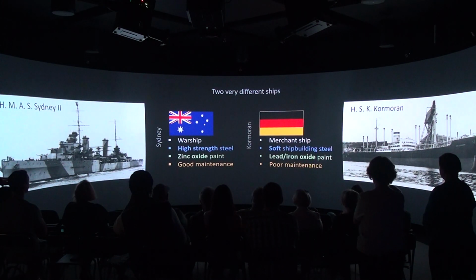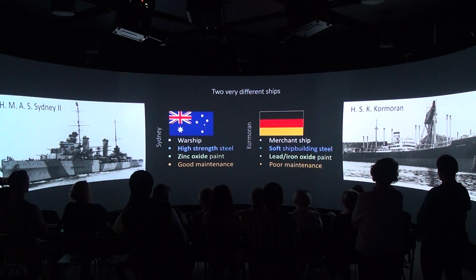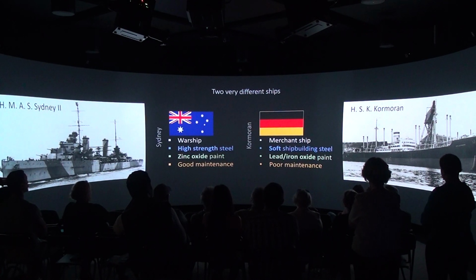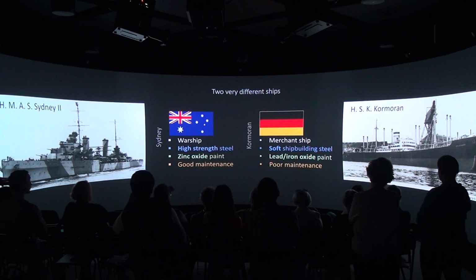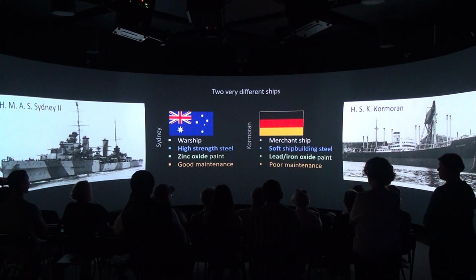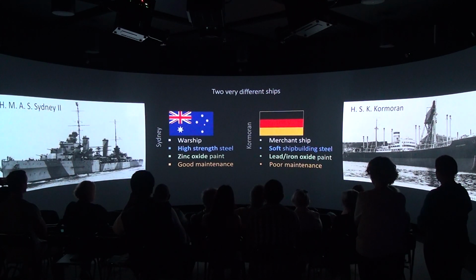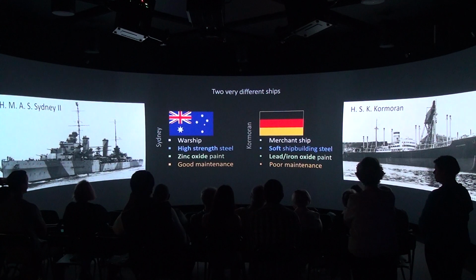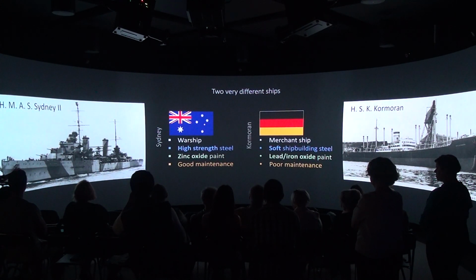And the Kormoran was a merchant ship converted into a warship. It was built with soft shipbuilding steel that wasn't designed to hold the impact of torpedoes. It had lead iron oxide paint, very poorly maintained, because the purpose of the Kormoran was as a raider, so it was just go around the ocean, sink as much as it can, and it had no time to go into a dry dock. The captain was also complaining about the amount of biofouling the lower portion of the hull, the underwater portion, was experiencing, that it was slowing them down, and that they had to every once in a while careen the boat and scrape all the green muck that was present in the hull. But they couldn't ever go into a dry dock.